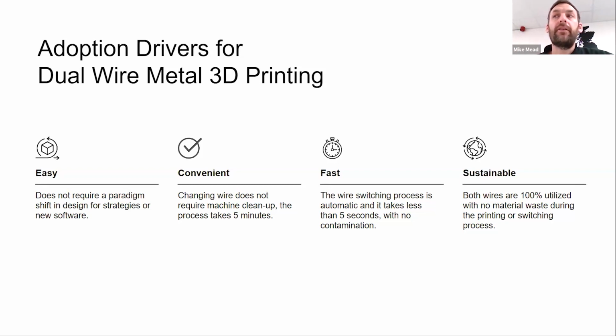And because of the Meltio process, with no spatter from the part as you would get with a WAAM process, 100% of the material is used within that part. So you're not getting contamination between your parts, but also 100% of your material is used within that part.